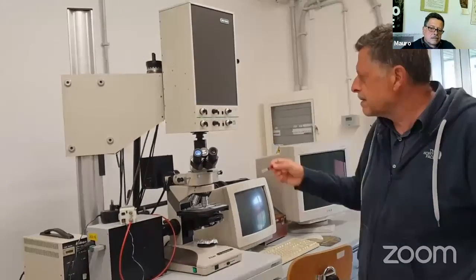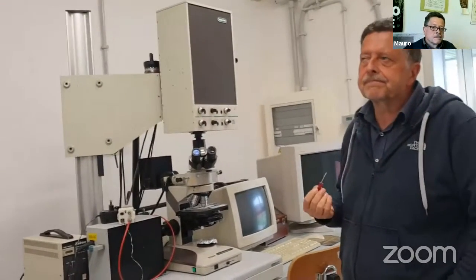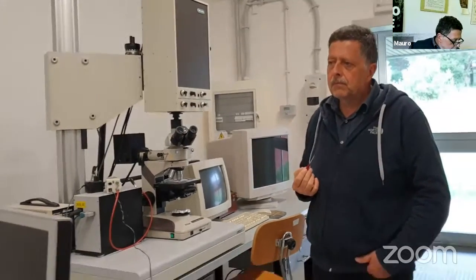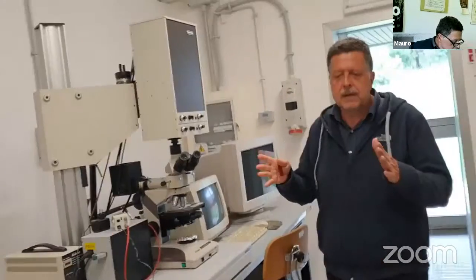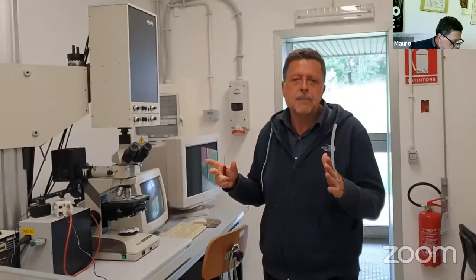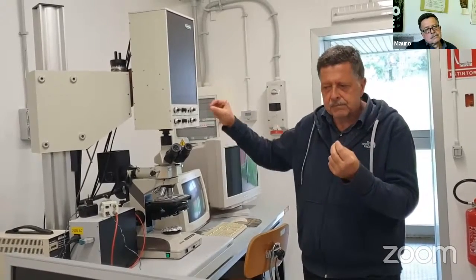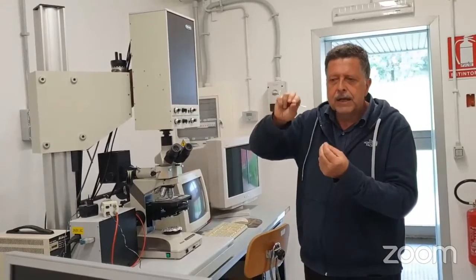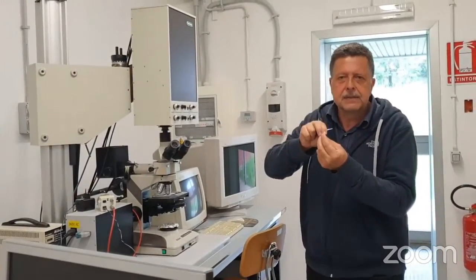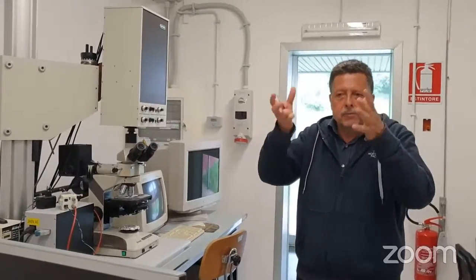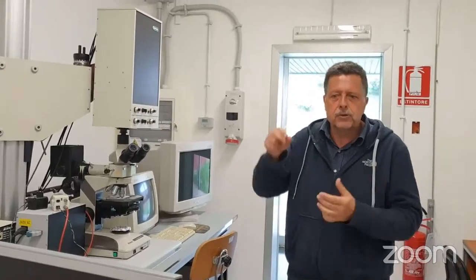What is important of this system is that it has a very high spatial resolution. It can build a luminescence map with very high resolution, down to 1 micron more or less, because there is an optical arrangement which avoids measuring the luminescence emitted from anywhere other than the focal point of the laser. So using this confocal arrangement, you can only measure the light emitted at the focal point of the laser. In this way, you avoid all the out-of-focus contribution. So you have a very precise definition of the sample emitting light.